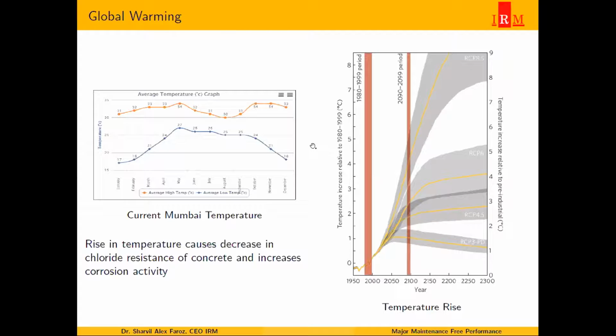Now, if there is just a 1 degree rise in temperature, the corrosion activity will increase by 47%. So just imagine if there is a rise of 4 degrees, how fast the corrosion will take place in our bridges. Therefore, if we can take this increase in temperature and how it affects our corrosion activity at the design stage itself, it will really benefit us. Therefore, it is necessary to take global warming into consideration.